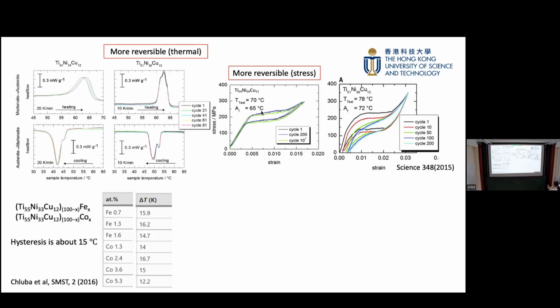And then if we test this material under stress, this is the stress-strain curve. If we load it, uniaxial loading, we have the stress-induced phase transformation and achieve the superelastic strain here, which is due to the stress-induced transformation. And then we have martensite here, austenite here. And these two materials: the thermally not so reversible material has much better reversibility in stress-induced phase transformation here. But the thermally more reversible material shows very prominent degradation under stress.